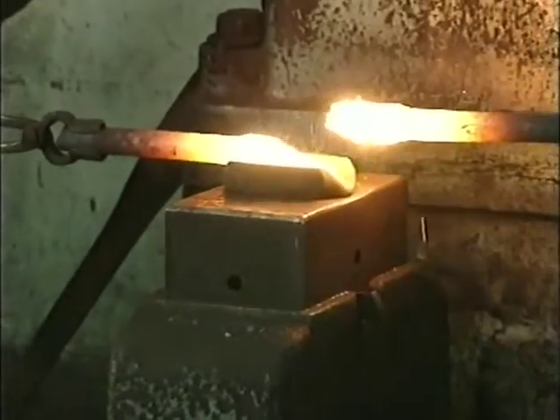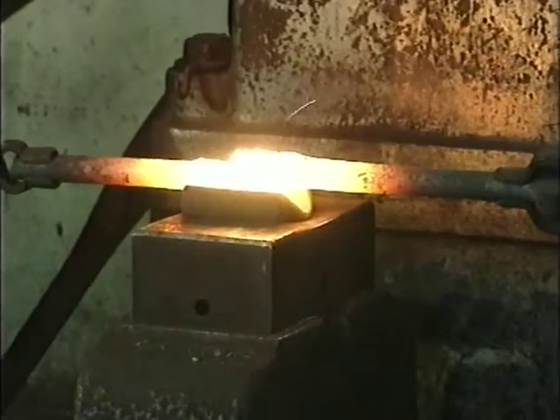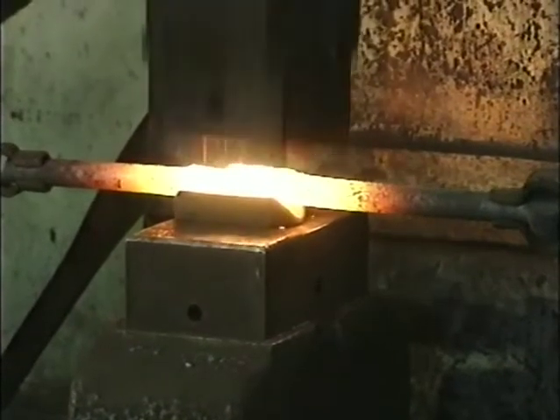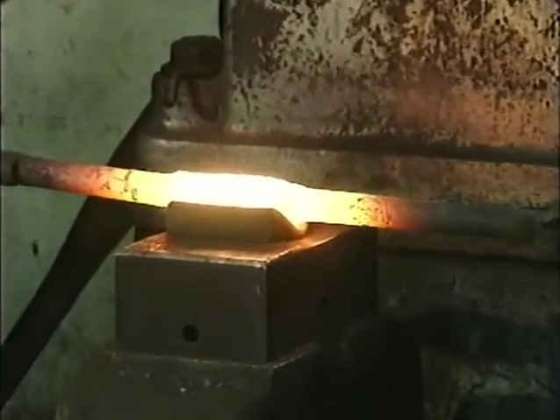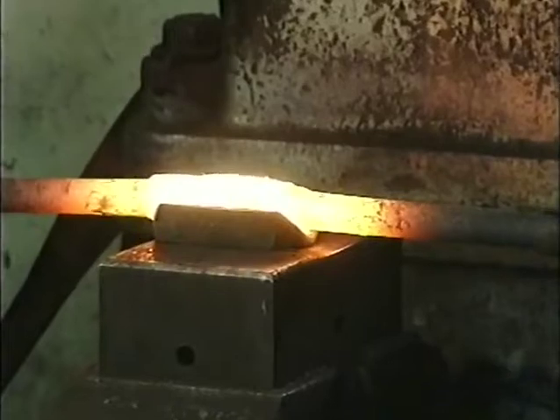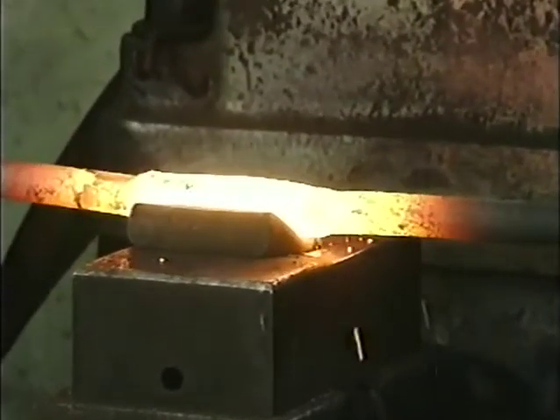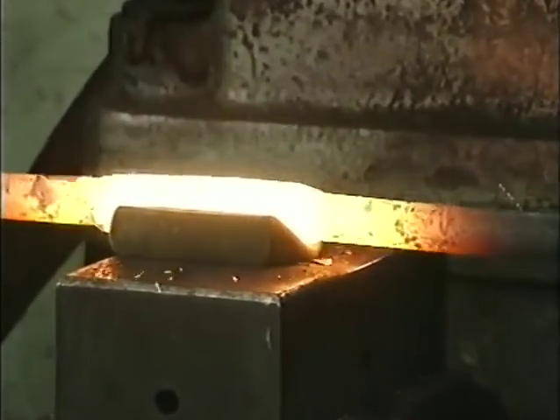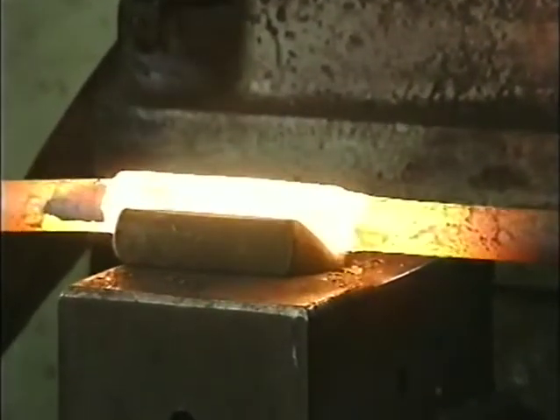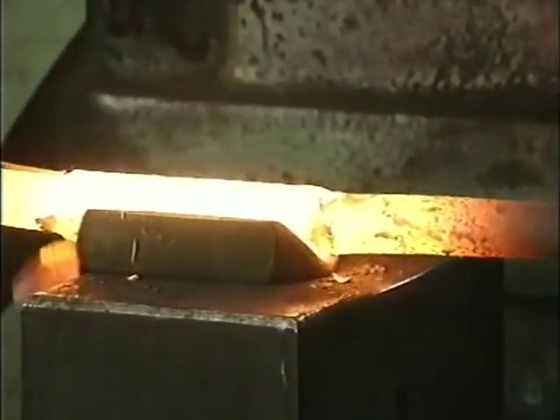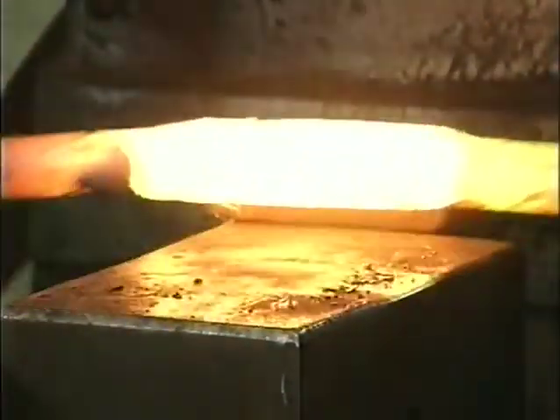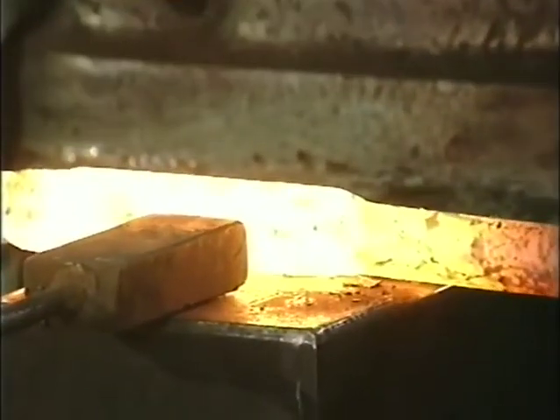And then you get them up to a welding temperature in the coke forge till they're nice and pasty and melting. Then you bring them out quick under the hammer, lay one on top of the other and hammer it in and it fuses it together. And then you just hammer it down to a peg till you get to the right size and then swage it. And if you're lucky, it's a good solid weld.